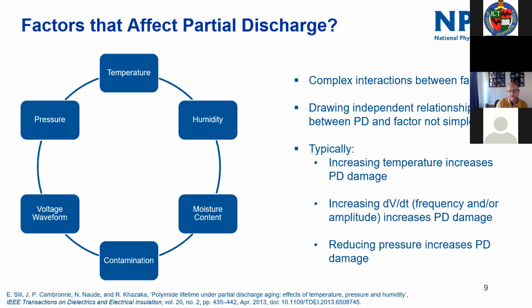One of the areas that we don't understand very well in organic dielectrics is what the parameters are that affect that breakdown voltage, that degree of partial discharge damage. It's certainly the case that the voltage waveform, as I've already said, plays a large part in it. However, we shouldn't rule out the fact that just because you've got a DC voltage, you can't have partial discharge, because of course, if you're switching that DC voltage, then you've effectively got a very slow square waveform. And so you will potentially get partial discharge every time you turn on that DC voltage and every time you turn it off.